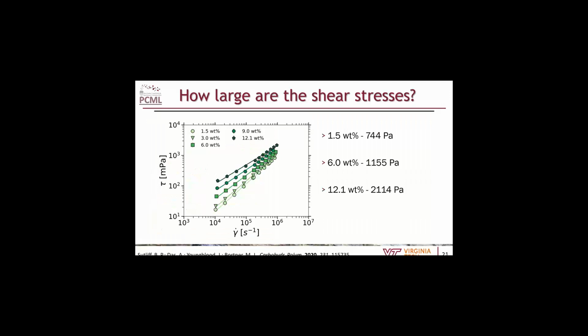So first we wanted to look at the shear stresses to see what magnitude they are. For our 1.5 weight percent, we're seeing 744 pascals. That's really not much. 2,000 pascals for our higher weight percentages, but this is still 2 orders of magnitude lower than what you would see in extrusion melting for things like melt fracture issues.